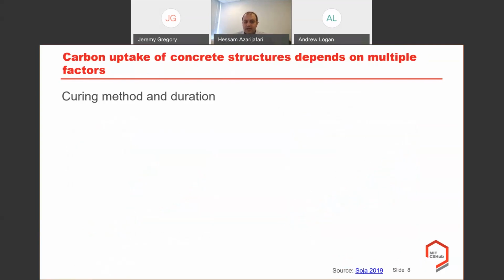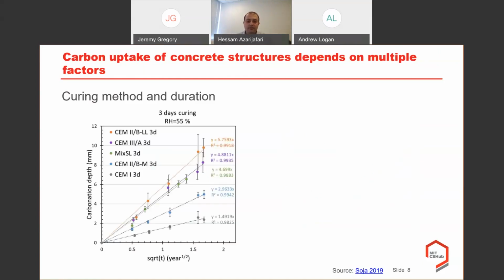Let's go to the next one, which is the curing method and duration. This is another factor. Once we are curing the concrete after it gets hardened to continue the hydration process, the concrete curing duration will affect the carbonation rate. Here is one graph that you can see. On the y-axis the carbonation depth, and on the x-axis you can see the square root of time, which, if you consider it as the number of years, can be considered up to 3 years. So a 3-year experimental investigation of the carbonation depth.